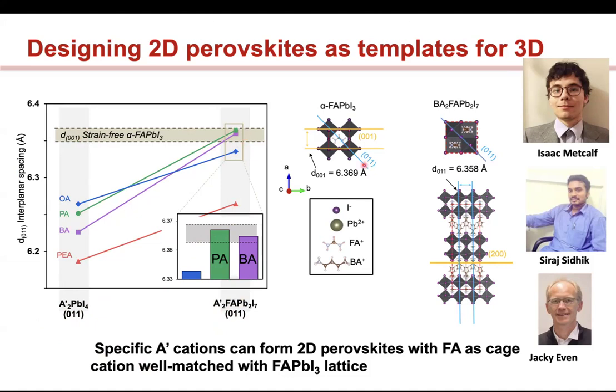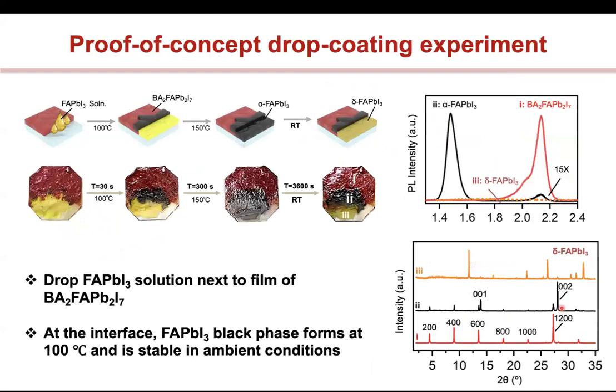So I've shown this here. This is the 0, 1, 1 plane. And you can see this alpha FAPI. This is what you want to do. This is 6.36. And if you take this 2D perovskite, now butylammonium, FA, then this 0, 1, 1 is very close. These two lattice constants are very close, which means that possibly I can use this to grow my 3D perovskite on top because these are lattice matched. Okay. So that was sort of the idea, and this was developed by us here in collaboration with Jacky Even, who is at the University of Rennes in France. And so the first experiments were very simple. What we did was we took these 2D perovskites on a glass slide, right?